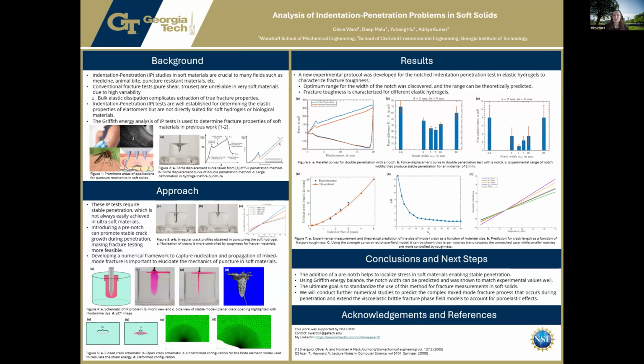In Figure 7, we compare experimental data with theoretical predictions, and the agreement between the two is very good, which validates our model. Another important observation is related to crack behavior. In very soft materials, cracks can form irregularly, as shown in Figure 3. However, with the introduction of a notch, we're able to control crack nucleation and guide it into a more predictable mode 1 opening pattern. This is significant because it allows us to directly connect experimental observations with theoretical fracture mechanics.